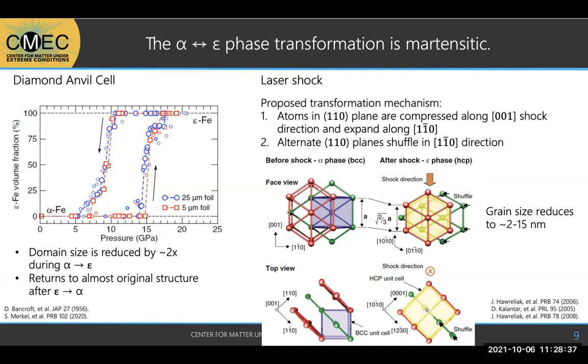And so these were, I think, a 2008 paper. And then a couple years later, or no, these were maybe 2006. But anyway, a couple years after these ones, Hawreliak also did an in situ diffraction study. Very similar experiments where they looked at what happens to the grain size. And so in this initially single crystalline iron, the grain size was actually reduced down to 2 to 15 nanometers, which is huge. It's a huge reduction. And it's honestly probably what engineers only dream of, because it would produce incredibly strong materials. But anyways, next slide.